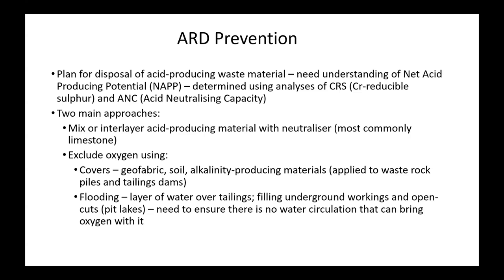So you basically need to know what the net acid producing potential of your waste material is, tailings or waste rock. And so you can analyse its CRS, which is its chrome reducible sulphur, which is an indication of the sulphur in the rock, which can oxidise to produce acidity. So if you just analyse for sulphur, you'll get sulphates and things like that as well, which won't produce acidity. Having said that, if you've got a lot of pyrite in the rock, it may not generate as much acidity as your CRS indicates. And then you also analyse the rock for its acid neutralising capacity. So limestone has a very high acid neutralising capacity, but even silicates will react with this acid and neutralise it to some extent. To use that information, it determines how the waste rock and the tailings are disposed of.